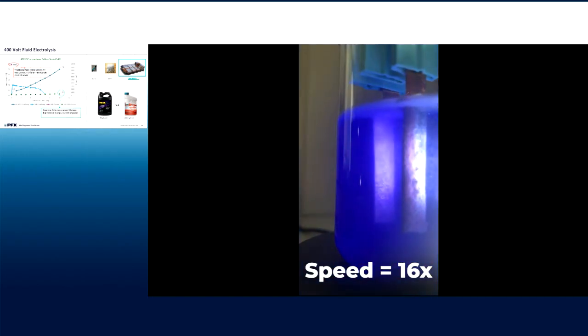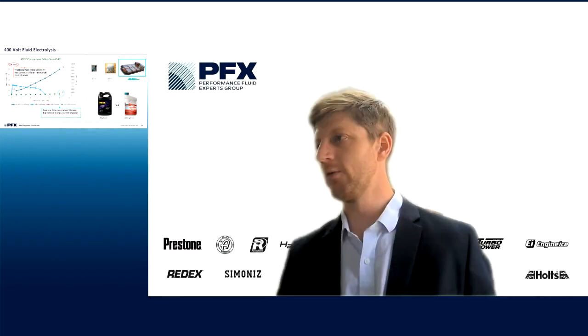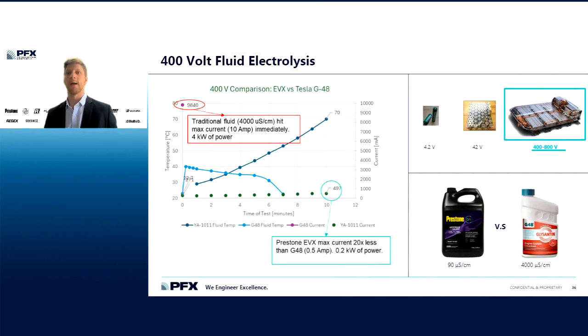So it's so mild that I was able to speed this up to 16 times, get through the entire 10-minute test video. A little bit of deposit buildup. Really nothing too aggressive, nothing too aggravating. I'll also note there's a hydrogen sensor set up in the test cell. As you pass current through the fluid, it will electrolyze the water and the glycol in the fluid and will generate hydrogen gas and oxygen gas, which as they combine can become explosive.